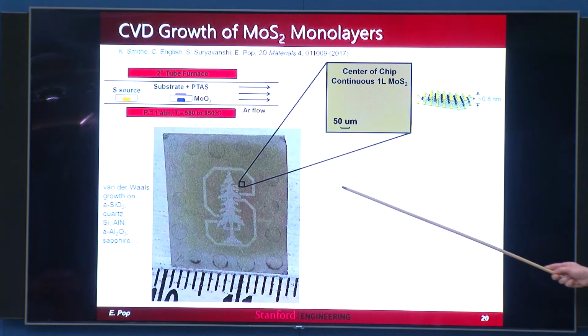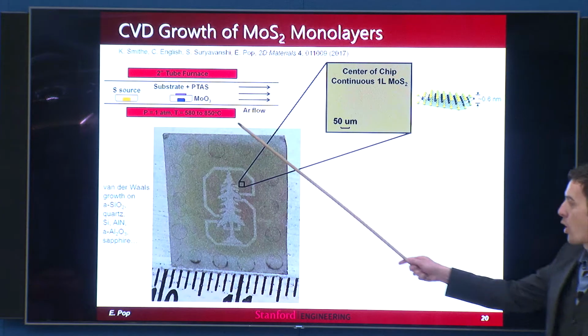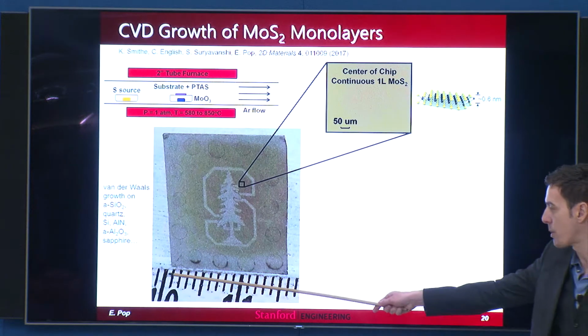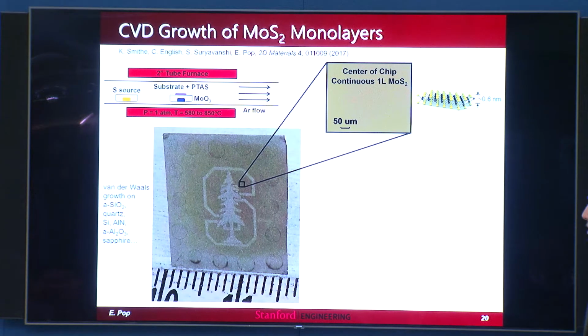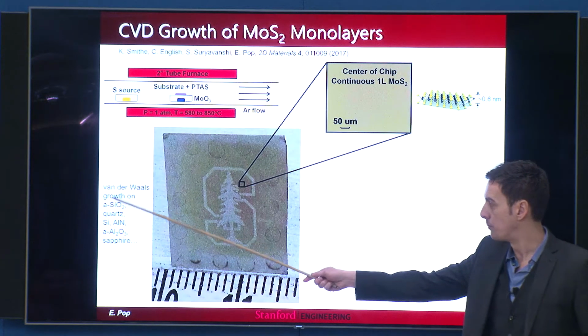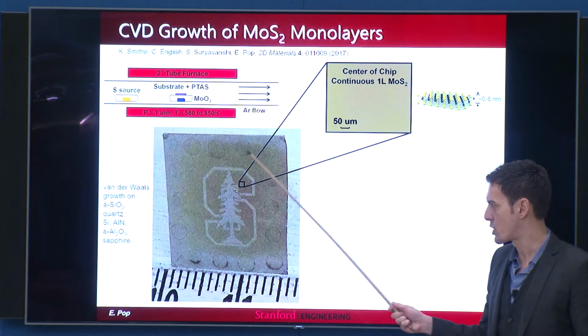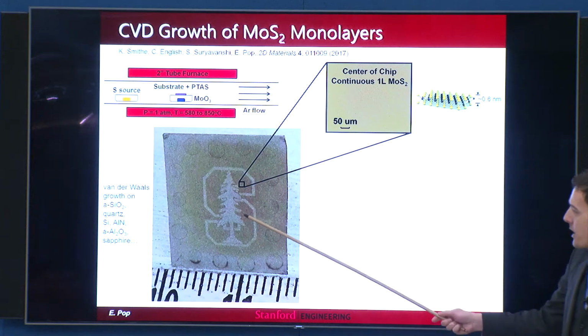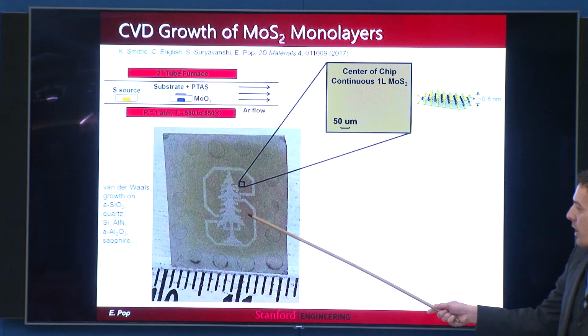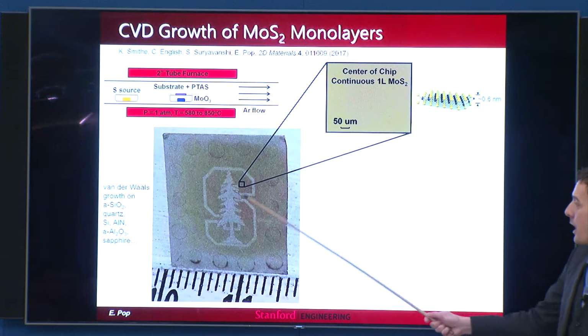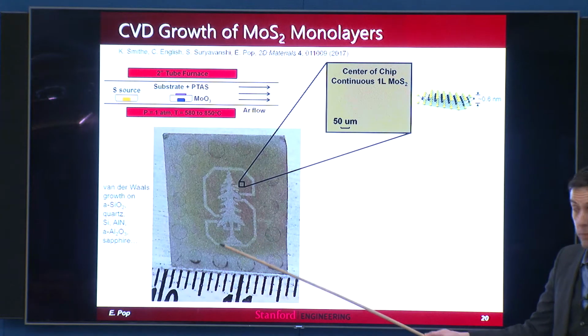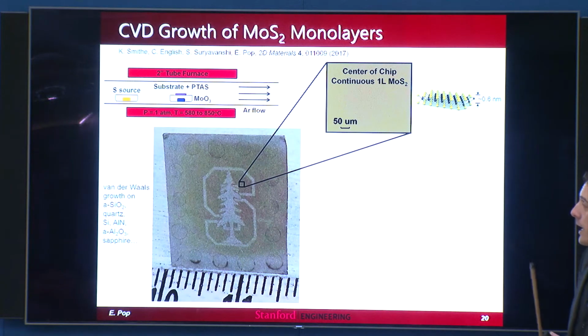Here's an example of basically this monolayer film grown over a centimeter scale. This is about 1.5 centimeters by 2 centimeters, the obligatory Stanford logo in the middle. But this is, by the way, etched. This is just directly etched into it. So you're seeing the contrast between a monolayer material or 3-atom thick material and no 3-atom thick material. That's actually pretty cool that you can see that with the naked eye.